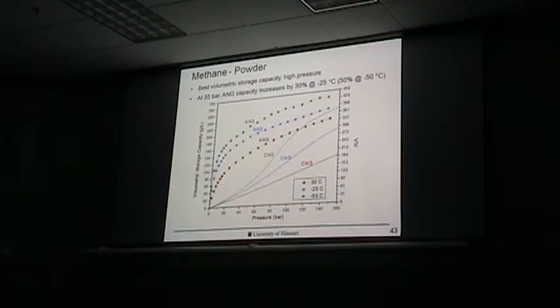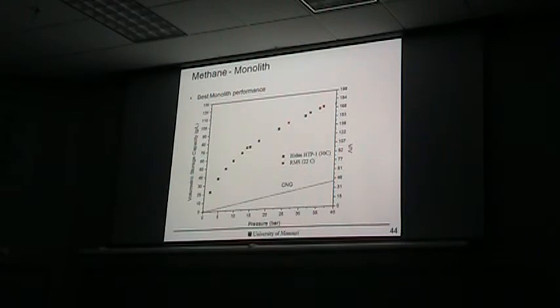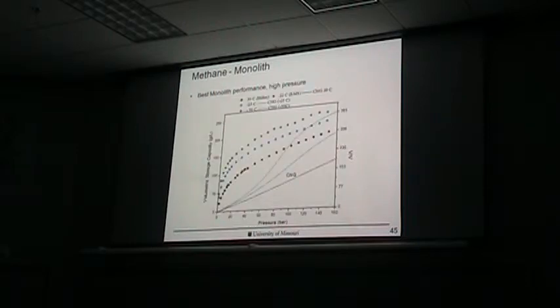This one goes up to 160 bar, and you see that these materials have a very big advantage from 0 to 80 bar. You see this here. These are all the absorbed materials, absorbed natural gas, and this is the compressed ones for different temperatures. You can see the main focus, we focus mainly on this pressure, because that's where we gain most of these materials. And at high pressure, we gain a little bit, but not too much. And this is here for the monolith. And again, this is for different temperatures for the monolith.